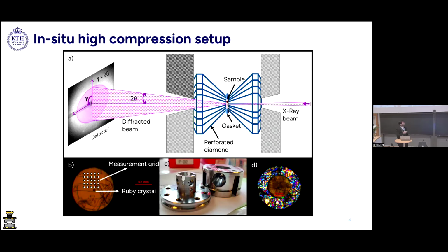This was the experimental setup where you can see the tiny amount of sample is compressed between two diamonds. There's a ruby crystal which is helping us to find out the actual pressure during the experiments. The X-rays are coming in, they are detected at the detector, and we found the diffraction pattern of the cellulose through this. In image B, you can see there is a measurement grid, which basically means we have measured the cellulose sample in different areas. This was also to prevent any of the radiation damage that we may get during the synchrotron experiments. This experiment was conducted at the extreme conditions beamline at DESY, Germany.